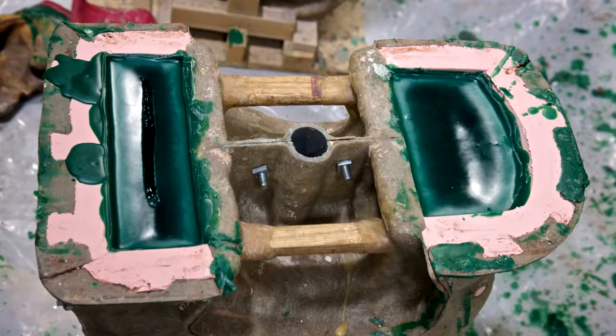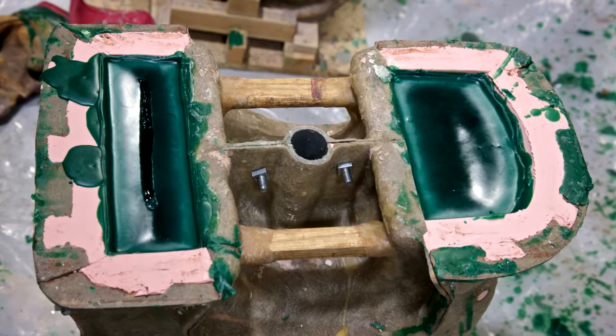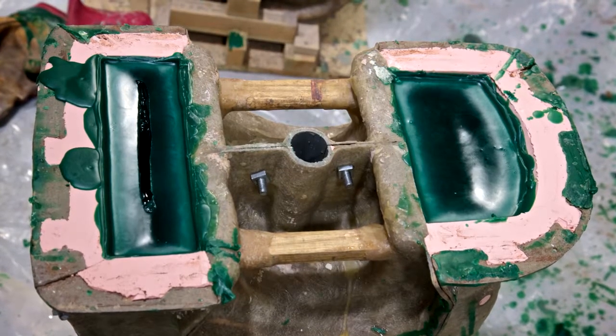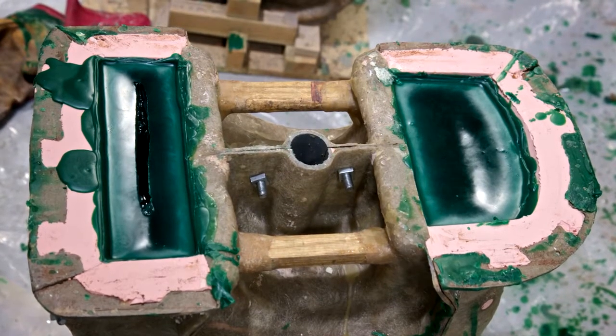So essentially what happens is that the longer I leave the wax in the mold before I pour the excess out, the thicker it gets. I normally wait about 20 minutes to get about 2 centimeters thick wax cast. After I pour the excess wax out, I then wait about 2, 3, 4 hours. Sometimes I just wait till the next day.